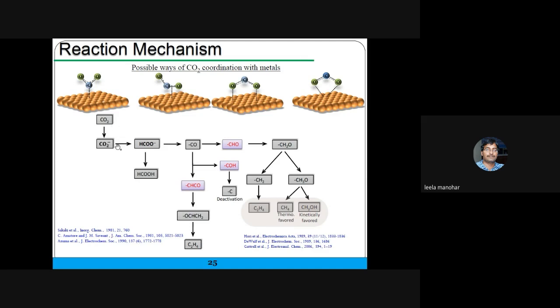First, the carbon dioxide will obviously be in a bent structure, and by taking electrons will form CO2 minus. From there, taking protons we form formate, then we get formic acid. The intermediate again gives CO. The protons then give CHO or COH, CH3O. Again we form CH2O or CH3O. Based on that we get methane or methanol. Is it thermodynamically favored or kinetically favored? It is one at the expense of the other.